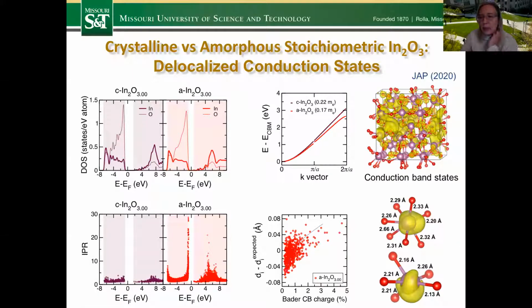Let me choose actually a pointer. What you can see is that not all atoms contribute to the bottom of the conduction band. It's not quite uniform. Some atoms contribute more than others. And we actually developed some understanding of how these electronic contributions can be predicted based on the structure, looking at the coordination, distances, expected distances, distortion. We found the dependence of which atoms contribute more. But if we focus on the atoms that do not contribute or contribute very little, these are typically the fully coordinated indium atoms, 6 coordinated, similar to the crystalline material. Then we can look at the distribution of those atoms.